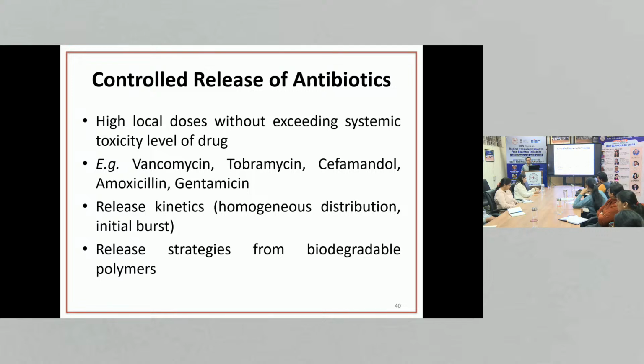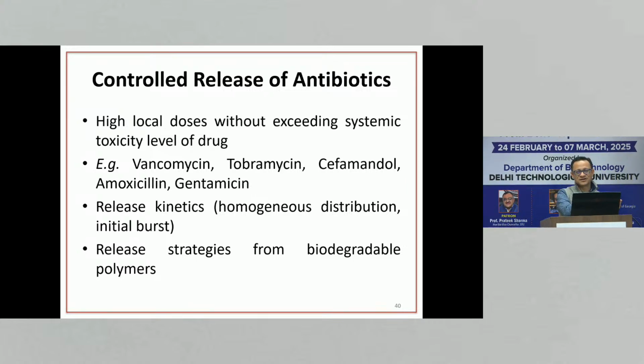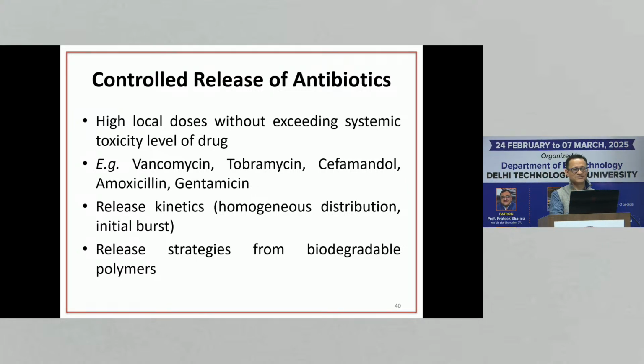Now, we cannot use biodegradable for vascular catheters because we don't want the catheter to start breaking, because the tube's role is not to break. Also, you have to remember, if the coating is biodegradable and it's breaking, you are making the surface rougher and rougher. Part of the polymer is breaking, part is still there. Now surface area is increasing, and as soon as you make the surface rougher, proteins will start adhering to that surface, and now the clotting problem will start. So we cannot do it all the time.